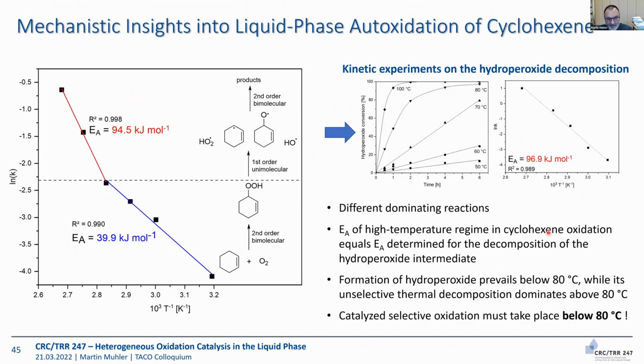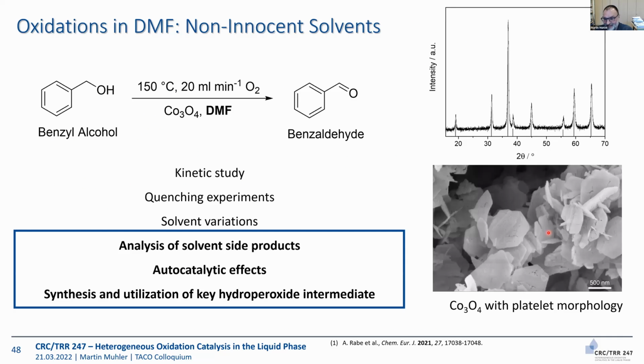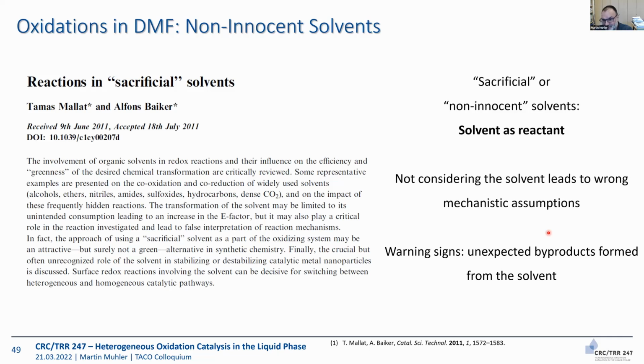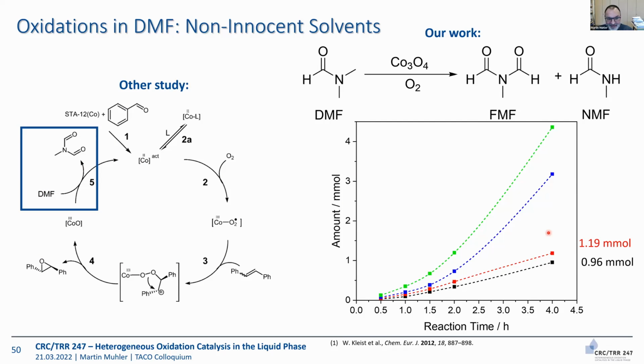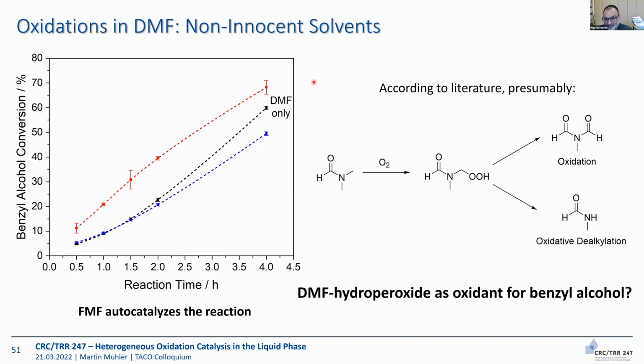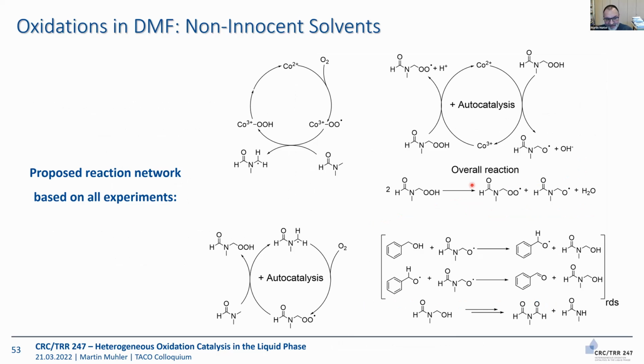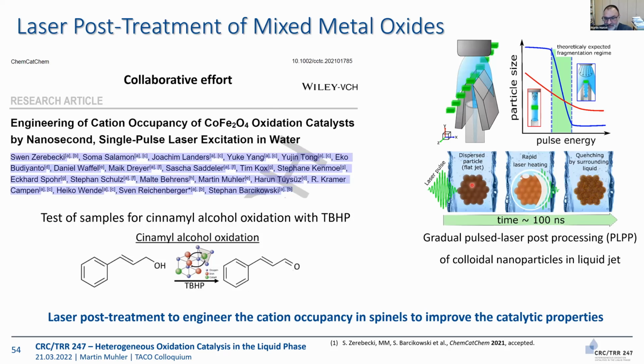And okay, then I'm jumping to the end. Last warning, you also have to check whether your solvent is really inert. And we made interesting experiences using another solvent. And actually this solvent is then part of the catalytic cycle because under reaction conditions it is converted to a hydroperoxide and takes part in these radical chain mechanisms.